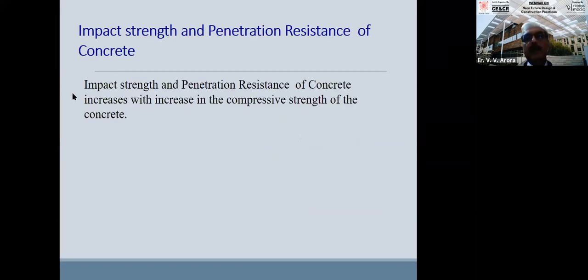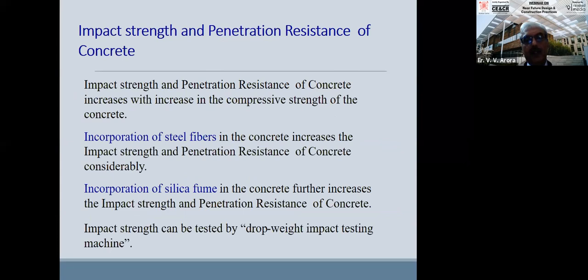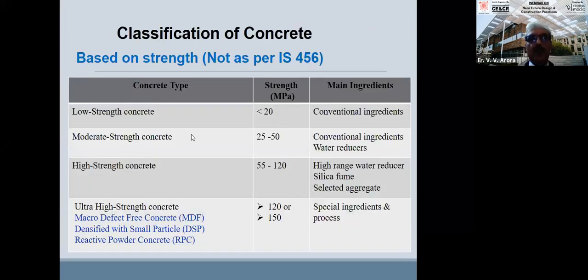Similarly, impact strength and penetration resistance. Incorporation of steel fibers increases the impact strength also. And silica fume also increases these properties. We do have test methods for this. Drop weight impact testing is there. For abrasion also we have got the tests. But then we have to decide the specification.